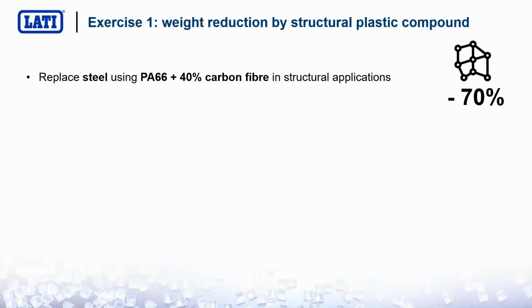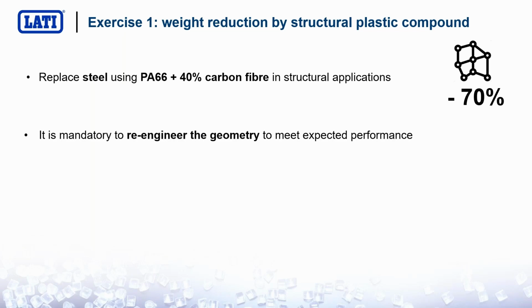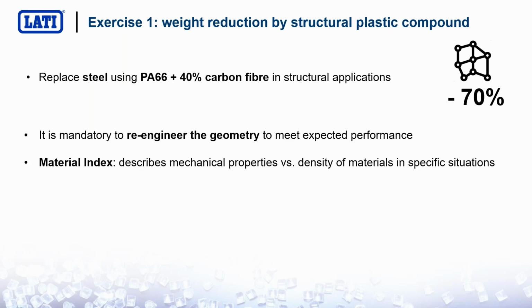Let's do an exercise. Let's suppose we are able to replace steel using nylon 66 and 40% carbon fiber, typical injection moldable or composite, whatever. The weight reduction is 70%, but of course it is mandatory to re-engineer the geometry of the part because you need the same structural performance. So you need to change the geometry of the plastic part. You will have to increase thicknesses, put ribs or whatever. So you have to take into consideration what is called the material index, describing how much mechanical performance is actually delivered with that very material.